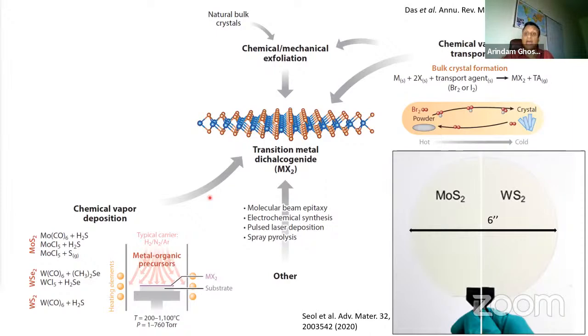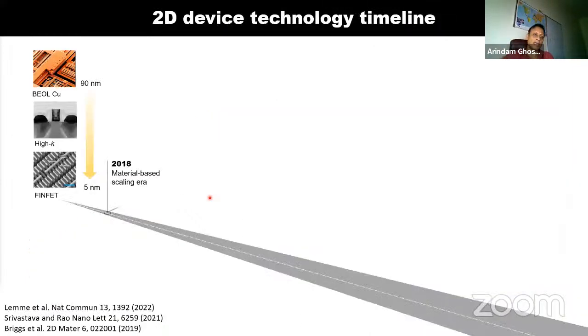So that's very good. So where are we with the technology? By around early this century, in the first decade of the century, the standard Moore's law scaling was almost over. Essentially, since 2005-6 onwards to 2018, what we are calling the material-based scaling era, in which you are no longer making the silicon in our devices any smaller, but you are looking at copper instead of aluminium in interconnects. We are putting high-K dielectric in semiconductors.